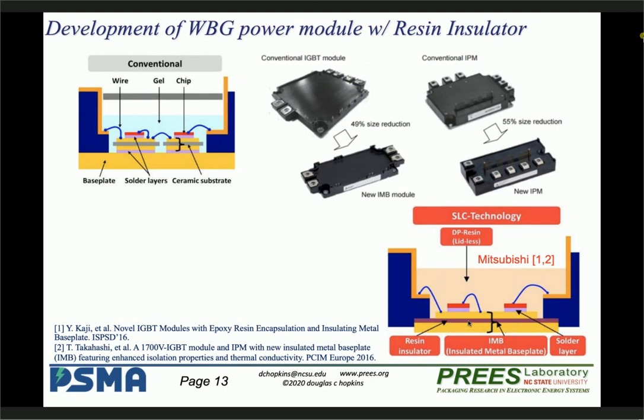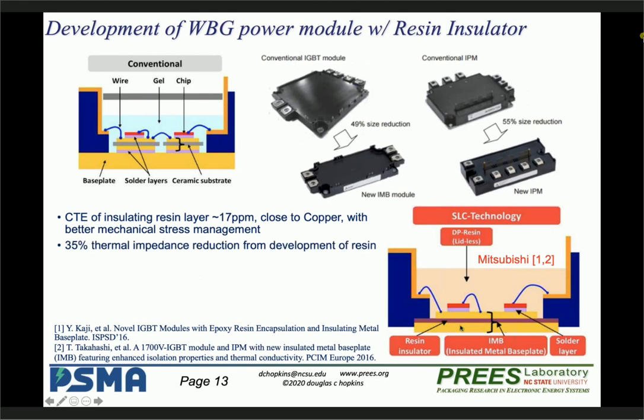It's the electric isolation layer, like you would have for DBC, which is copper bonded on ceramic, but the purple layer, instead of being ceramic, is going to be some kind of an insulating layer. In their case, the resin, organic epoxy. And what they show is that the CTE is much closer to copper, so you're matching copper to organic to copper. Next, you get a 35% increase in thermal performance. And we'll talk about this in the next slide, because the key to the organics is dropping the thickness down.